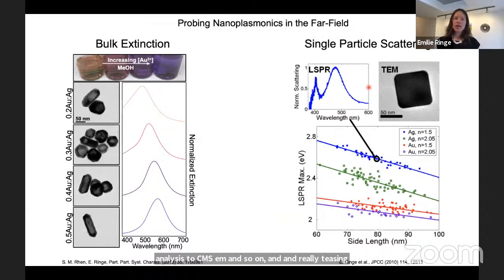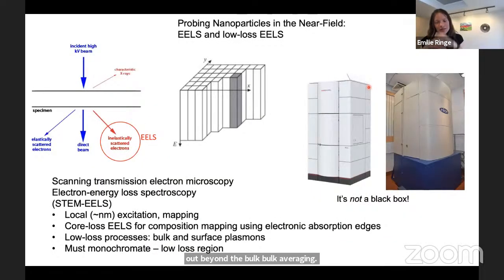There are other ways to probe the particles in the near field, and that's what we've been doing a lot of in my group: electron energy loss spectroscopy. This is done in a TEM, where you're sending a high energy electron beam in transmission mode, and then looking at electrons that have been inelastically scattered by some process.